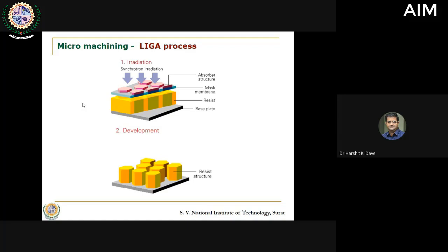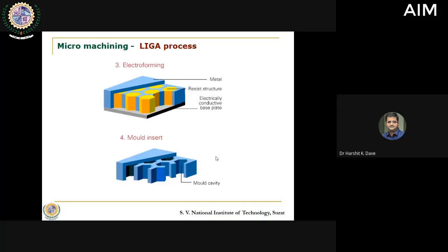You have a mask membrane and you have some sort of absorbers. So through the absorbers, the X-ray radiation is absorbed, and that is passed through the base material, and in that resist it is being protected. So here what you did was you put up a mask, and on the mask you put up an absorber structure. So there the radiation is absorbed by this absorber structure, this pink color structure, and the rest of the material is burned. So based on that, you get a structure of the base material. So instead of creating a cavity, you have created a full 3D design over it. Now this design is filled with the metal. Okay, so here you fill this with some sort of metal. You connect it with the electroplating process.